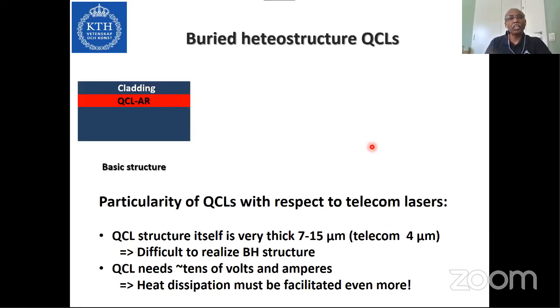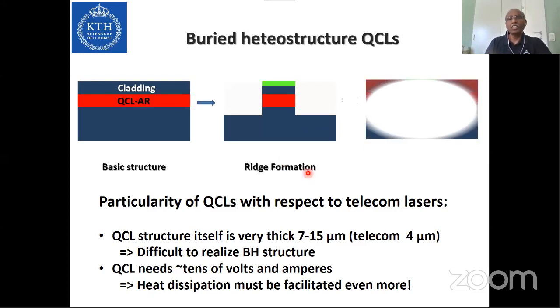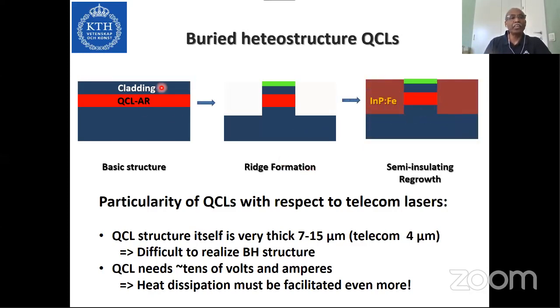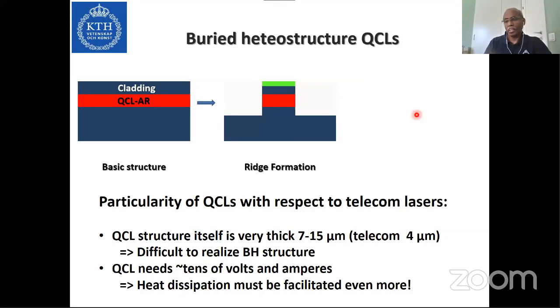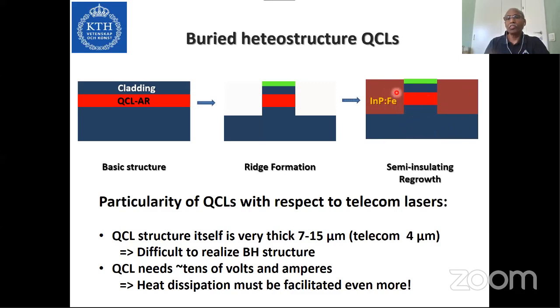What is interesting is, this is the buried heterostructure laser, how we fabricate. We have the quantum cascade laser active region, and we have the cladding, and you etch down, and then you are doing regrowth of indium phosphide, iron-doped indium phosphide. Now, the particularity with QCLs with respect to telecom lasers is that the QCL structure itself is very, very thick, 7 to 15 micrometers. So if you etch down and try to regrow this material, it is very difficult with other techniques. And that is where our technology comes, VPE comes.